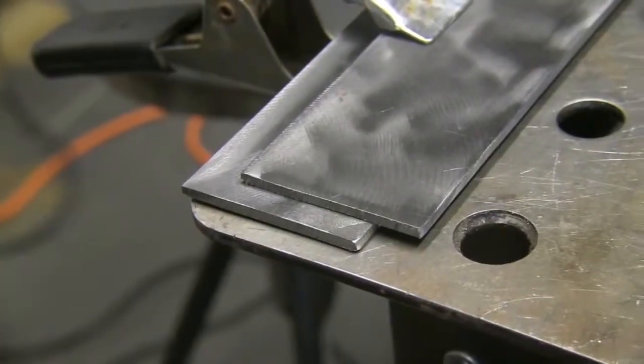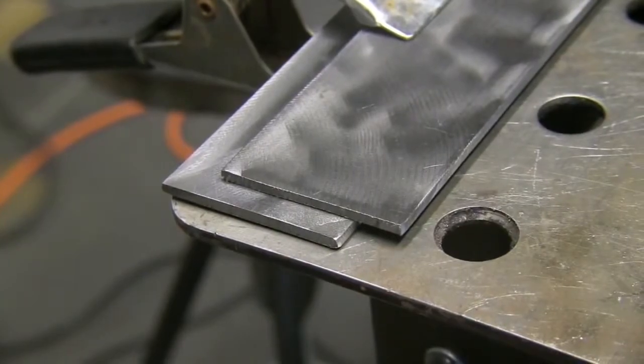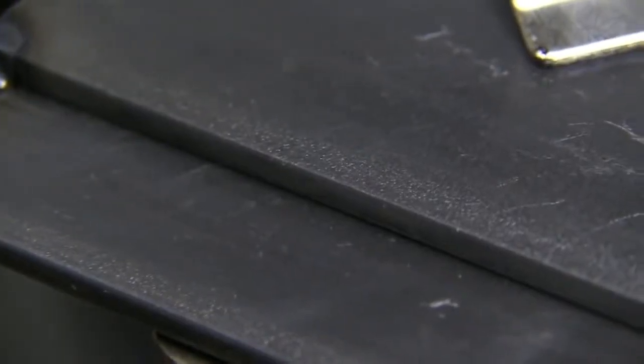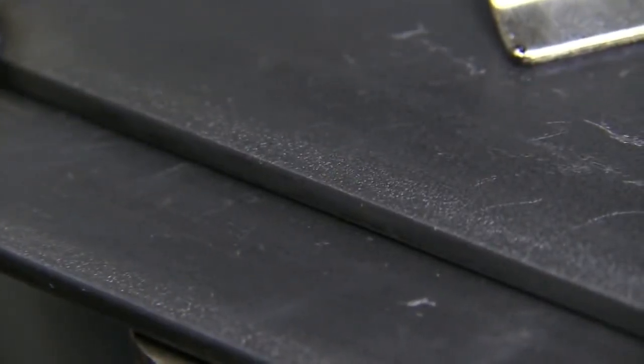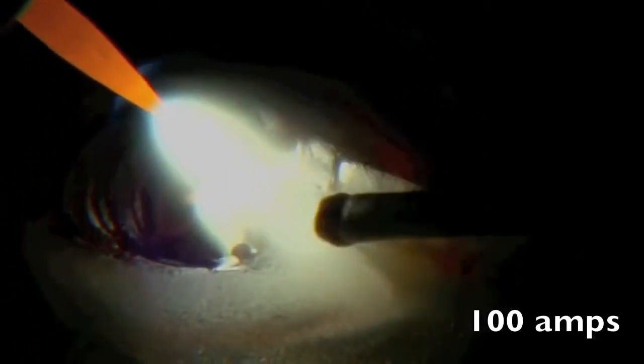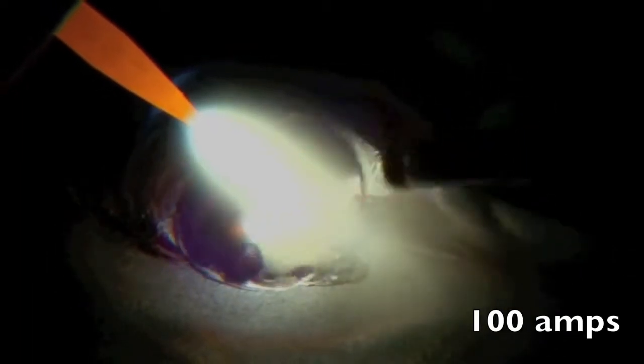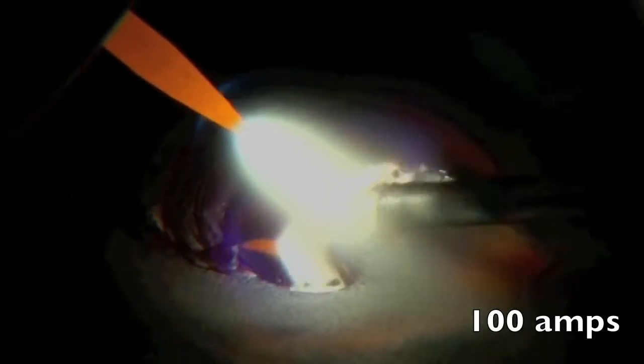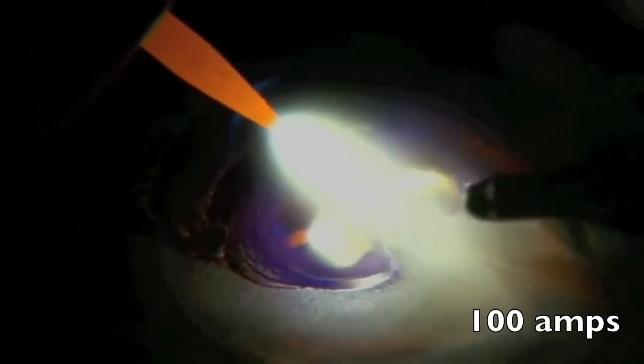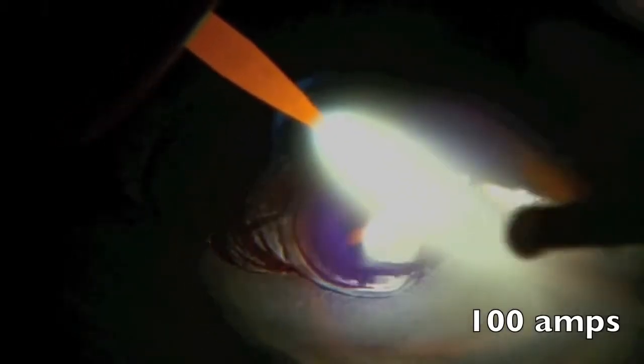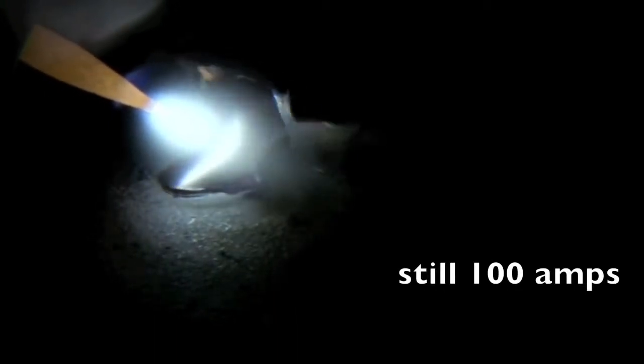So I set up a little lap joint here because a lap joint kind of shows this better than most joints. And it's 11 gauge cold rolled steel just wiped down with acetone. Now I'm holding a long arc, too much angle, and I'm not shielding that hot end of the rod with the argon. And see how things are going here. It's more like gas welding than TIG welding because there's a huge arc plume and there's a big heated area, and I am not taking advantage of the concentrated heat of TIG welding.